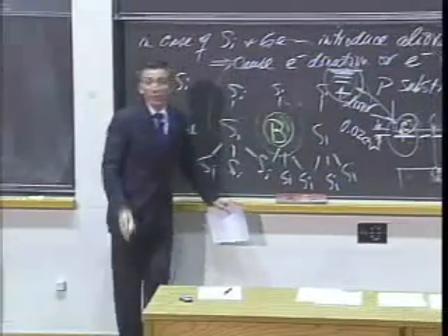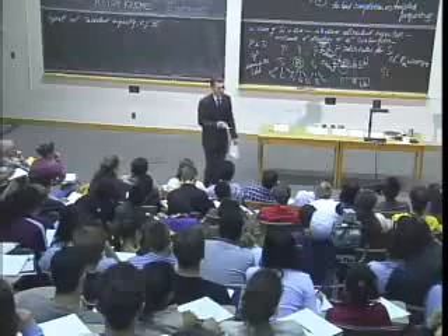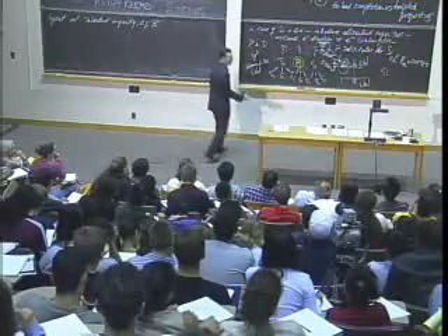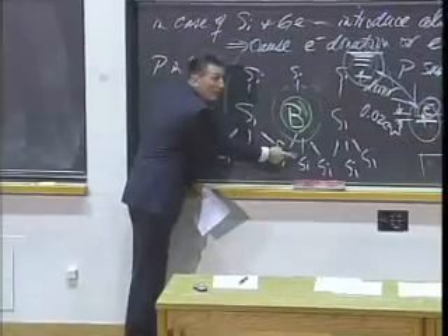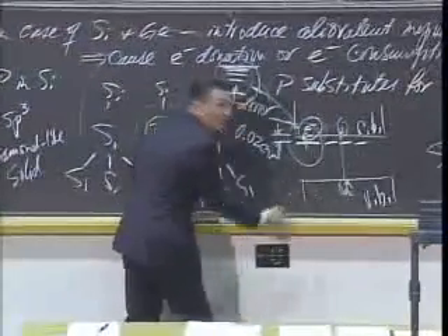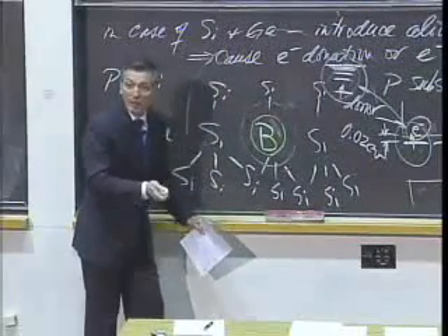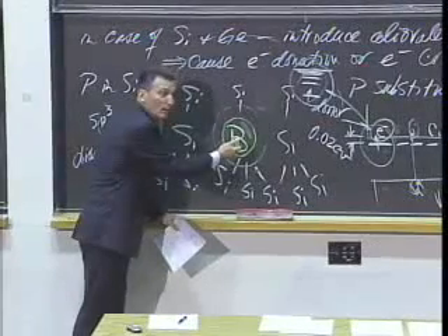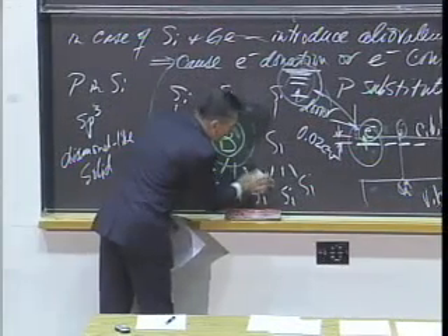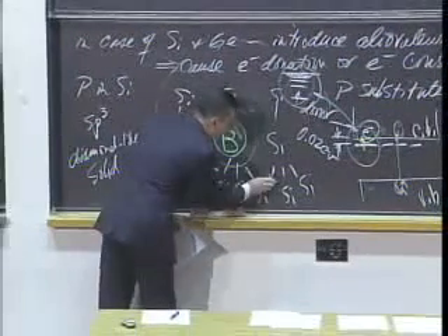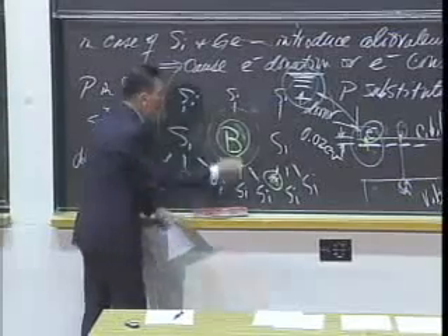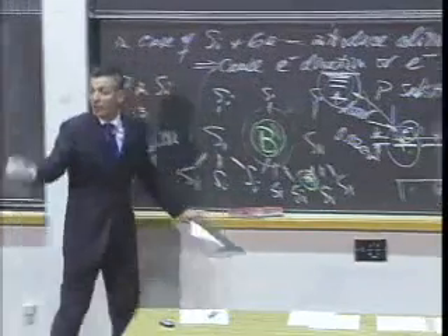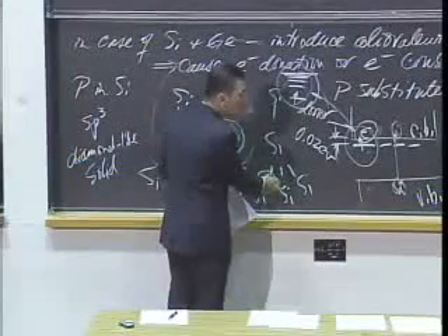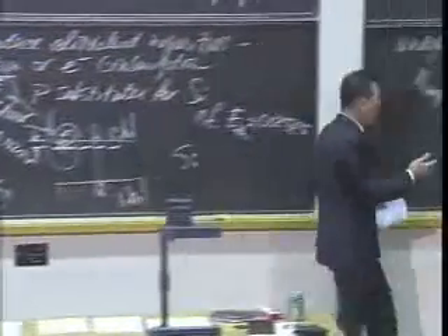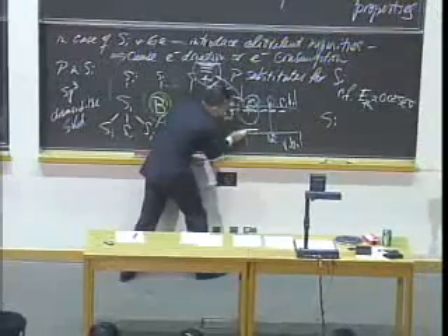lacking 1 electron? Where is the electron inventory in this crystal? Where's the electron store? If I go shopping for electrons, where's the only place I can find them? They're here. They're in the bonds. That is to say, they're in the valence band. So what will happen is we will rip an electron out of the valence band and move it over to here. And when we do that, what happens if I take an electron out of here? What's left behind? A hole. So let's generate a hole. So every time I introduce a subvalent impurity, I call for an electron out of the valence band and I generate a hole. And where's that hole going to lie? We can go through the same analogy and we will find that the energy level of that hole is sitting just above the valence band.